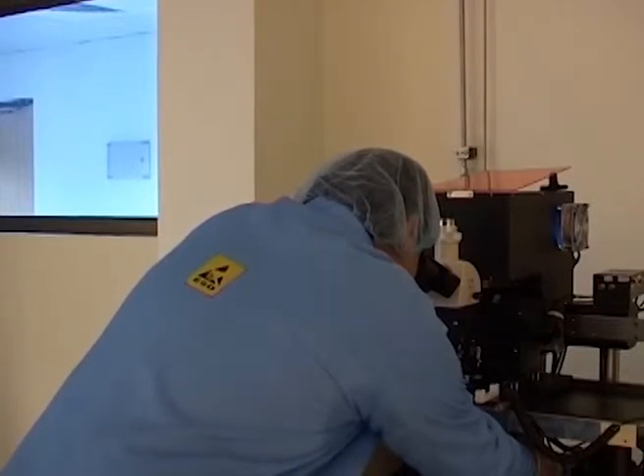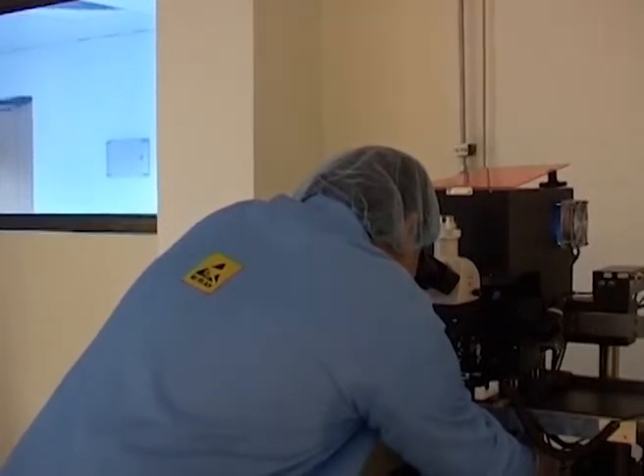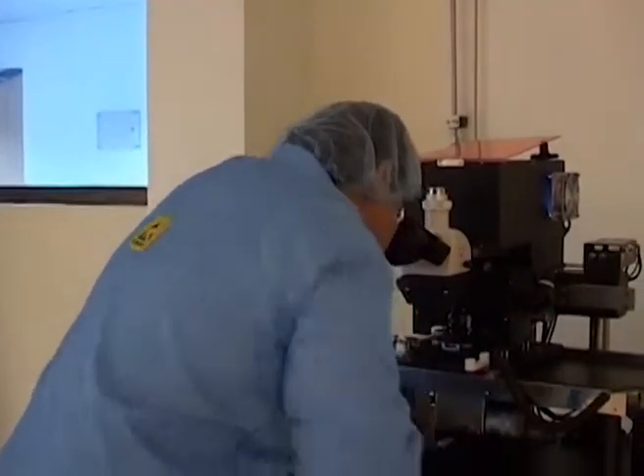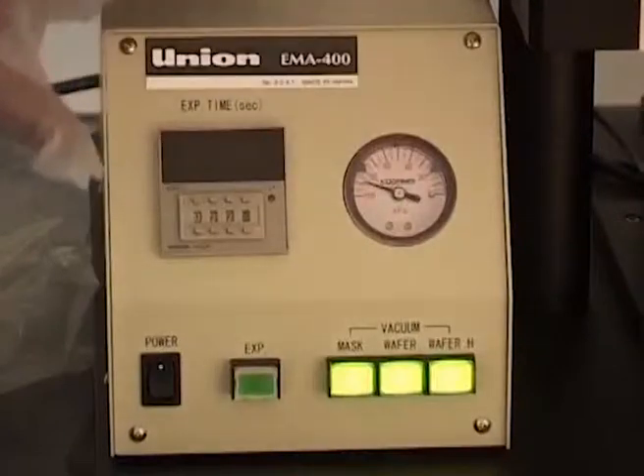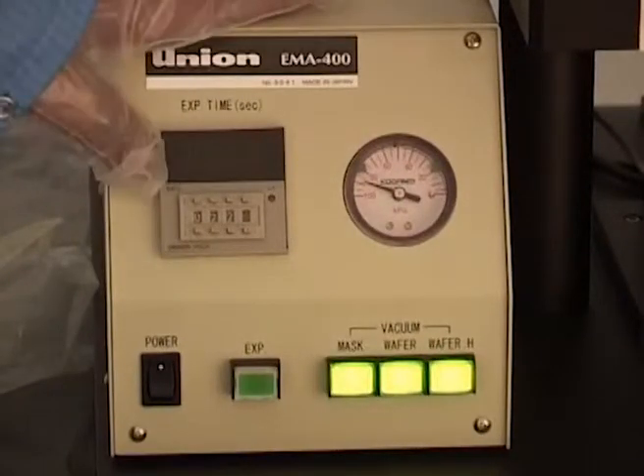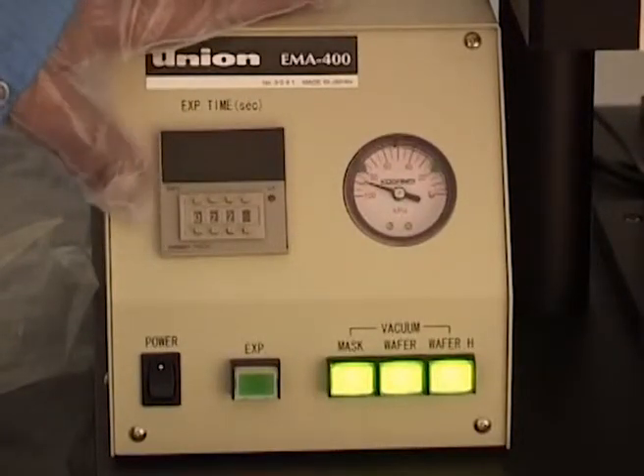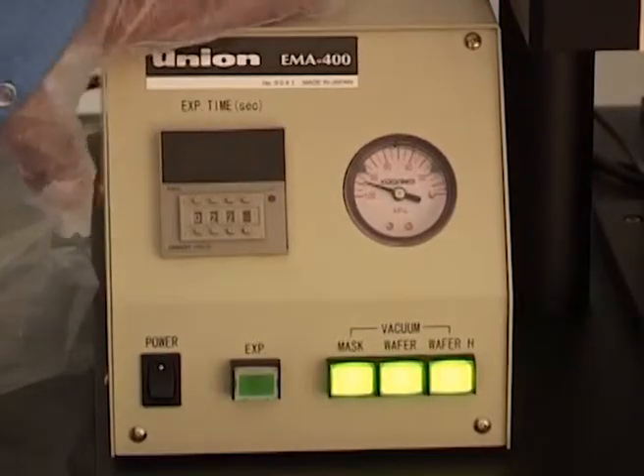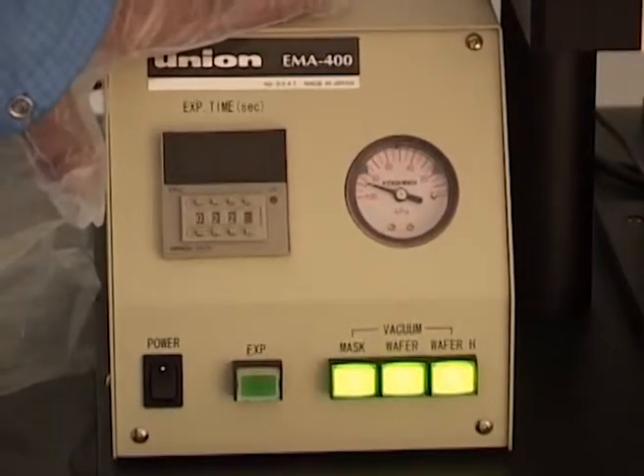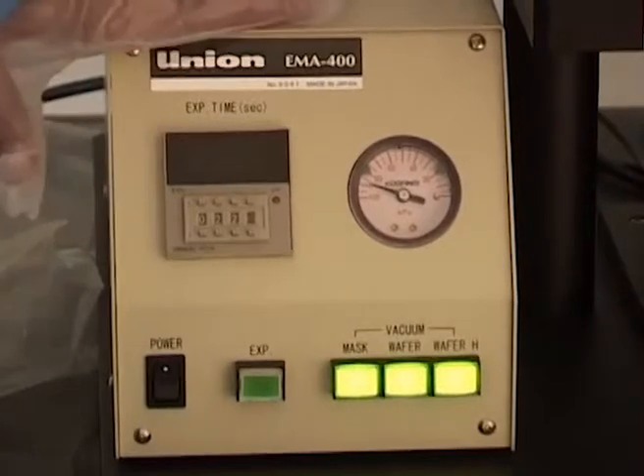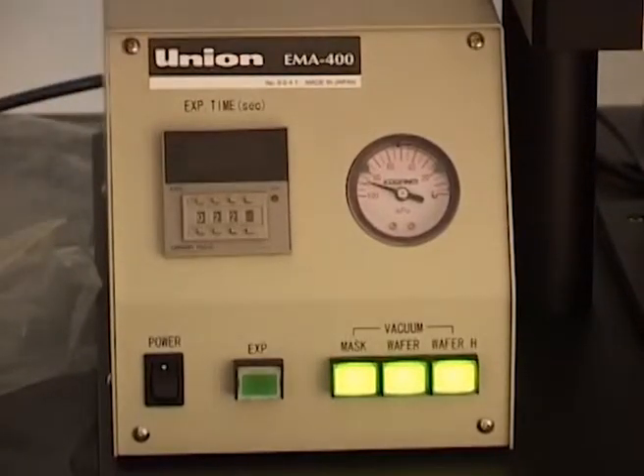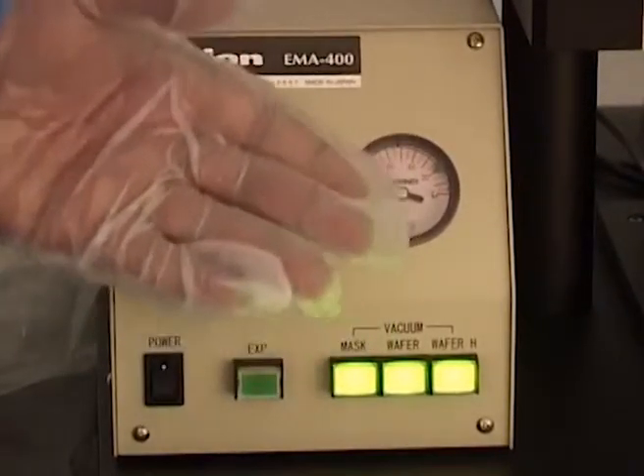Now I think we have really pretty good adjustment and we are all set to do the exposure. So this right here is also a controller for the exposure time. If you look at the resist manufacturer sheet, it gives the exposure dosage for a certain thickness of the resist film. So what we need to do is to calculate from there, using lamp power, how much time of exposure is needed for the particular thickness that we are operating.